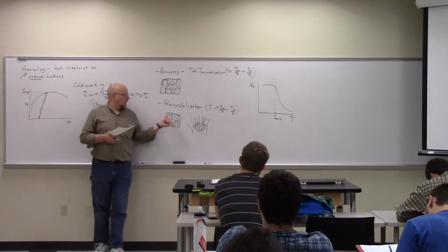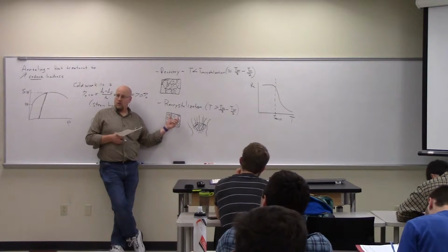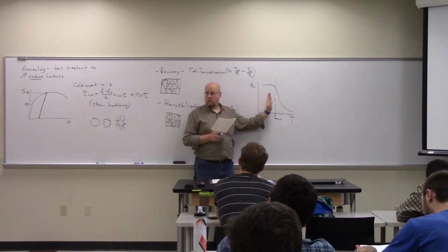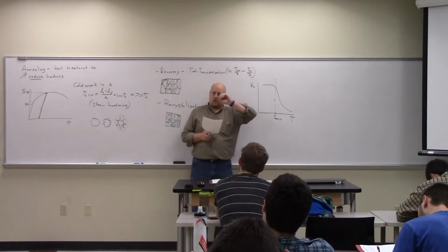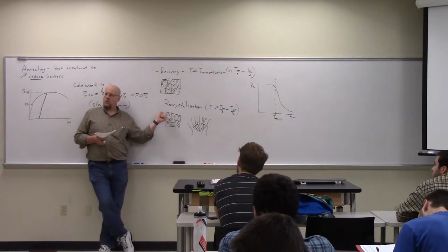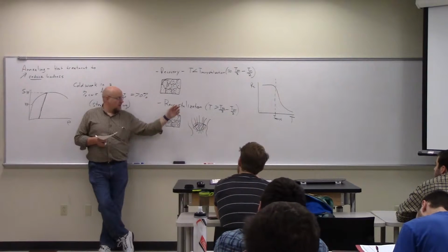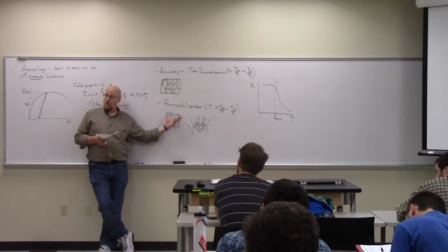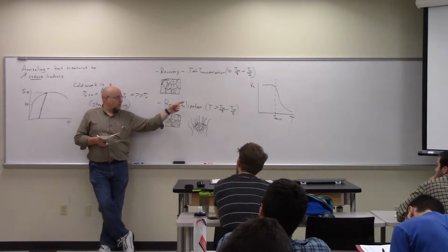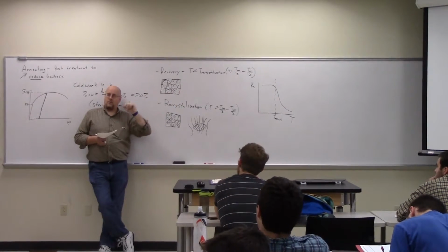is that these grains are allowed to grow. At a larger temperature, there's a bigger driving force for grain growth. So you're right. If I just start recrystallization immediately, or at the temperature just above it, I just get enough to grow smaller, slightly larger grains. Those slightly larger grains are only slightly softer than the material was before with all the strain cold work in it. But if I go to a high enough temperature that those grains can continue to grow, then I can actually get a softer material again. Or if I leave it at the lower temperature, just above recrystallization, but leave it for a long time, it's effectively the same thing.